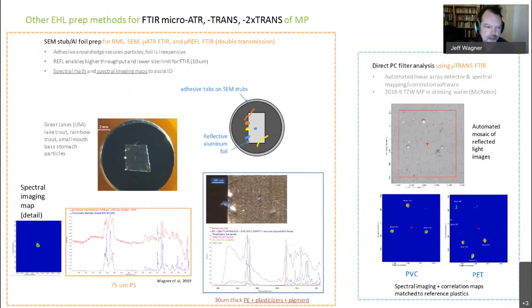There are examples in the bottom of using spectral math and spectral imaging maps to help identify these microplastics. In the middle, you see an example of various library spectra to add together and account for all the observed peaks in the unknown, in this case being polyethylene and several butyl phthalates, plastic additives. The Raman also found pigment